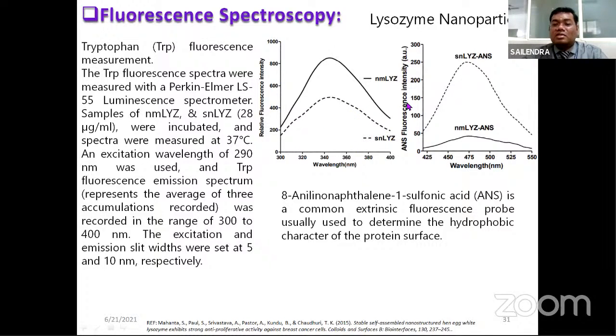Whereas you see ANS fluorescence intensity, that is another type of fluorescence spectroscopy, which you do to measure the surface hydrophobicity. So the nanoparticle surface will have a greater amount of surface hydrophobicity. In my case, it was very high hydrophobicity, and native lysozyme has very little hydrophobicity. So the advantage is, in lysozyme nanoparticles, I can load a greater amount of hydrophobic drugs.